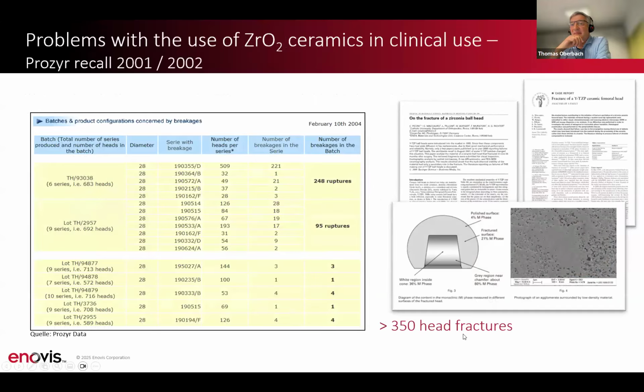But the worst impact of the use of zirconia ceramics for hip replacement was the so-called Prozyr recall, which was in 2001 and 2002. There was a French manufacturer, and they changed their sintering process from batch furnaces to tunnel furnaces, and they had two batches which showed micropores inside the balls after sintering.